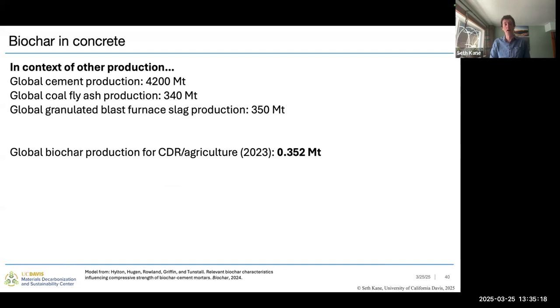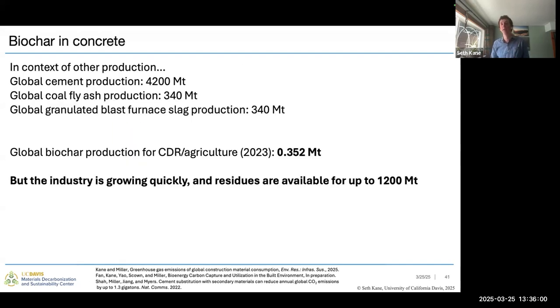So to put this in context of concrete and cement production and how much biochar we might be able to use, we currently produce about 4,200 million tons of cement, about 340 million tons of fly ash, which is one of our common SCMs that we're using today, and about 350 million tons of blast furnace slag, again, a common SCM that we're using today. So those are all pretty large numbers. In contrast, we're only producing about 0.35 million tons of biochar currently. So obviously that cannot be a drop-in replacement right now at this moment for those existing SCMs. However, this industry has been growing quite quickly. It's been more than doubling the amount of biochar produced annually the last couple of years. And of those total residues that are available, we could produce up to 1,200 million tons, which would be much more than we could use in that cement production at that 10% replacement. So there is a lot of potential.